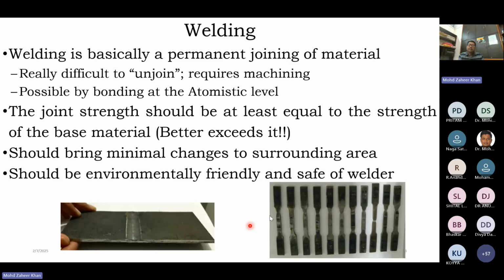And as you can see from the necked region, in all cases, the fracture is taking place away from the region where welding has taken place. So welding is there in the center. It is either breaking at the bottom or at the top, but nowhere is it breaking in the middle. The only specimen that has fractured in the center is this particular one, but in this specimen, no welding has taken place in this region. If no welding has taken place, it is bound to fail approximately in the middle of the gauge section. But when welded specimens are tested, they are not able to fracture in the center because the central welded region has higher strength than the base material. So in comparison to the base material that you have welded, the central portion of the welded region has higher strength, and therefore the specimens are breaking away from the welded regions.